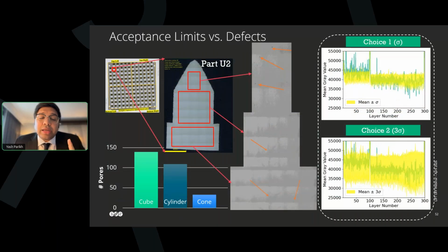All right, so that U2 part was split open. I said, without any post processing, we just took it off from the build plate. I said, get me the number of pores that you see through the microscopy, and we were amazed that this is a signature on the top right side of the part U2 for all 300 layers, and it's a mean plus or minus sigma from its moving average signature.